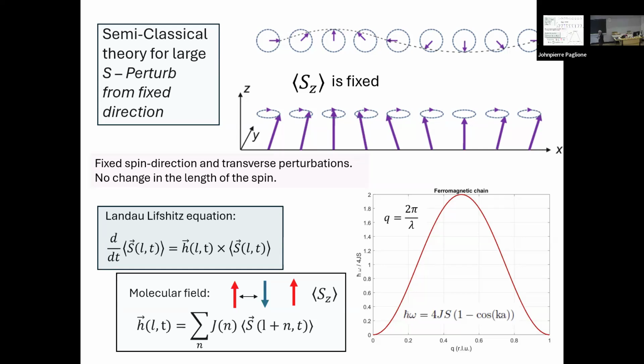And that's the idea with neutrons too. If you can measure the normal modes, the collective excitations that occur in the spin dynamics, for example, you can understand the underlying interactions. And a nice model for that is if you think about a magnetic system, which is made up of a series of vector spins with a fixed length, and you want to study collective excitations from that, you want to look at excitations that look something like this, where there's a weak transverse movement of the moments as you go over a particular wavelength.